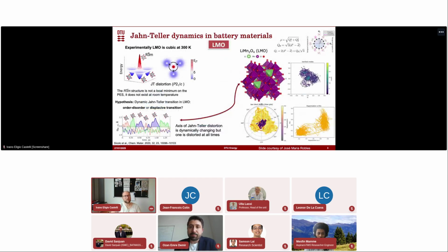Then you can look at whether there is an order-disorder or displacive transition, how the polarons change at different temperatures, and what kind of charge transfer you have. So you can see here, for example, in some of the Van Vleck modes, when you go from +3 to +4 charge, you can assess whether the polaron is here or has moved somewhere else.